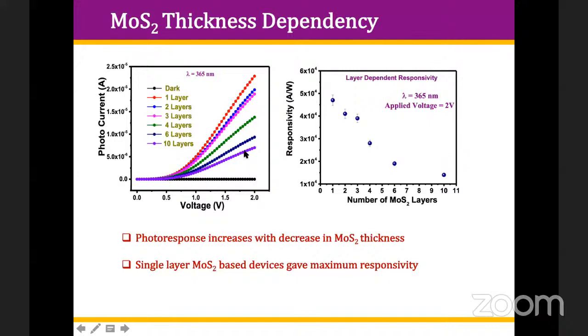And with 10 layer, this is the photo response. 6 layer, this is the photo response. So with the decrease in the thickness of this MoS2, the photo current starts increasing. Or you can say the responsivity of the photo response was found to decrease with the increase in number of layers, which gives the advantage of increase in surface to volume ratio. The fewer the number of layers, the better the photo response, better the responsivity, better the photo current.